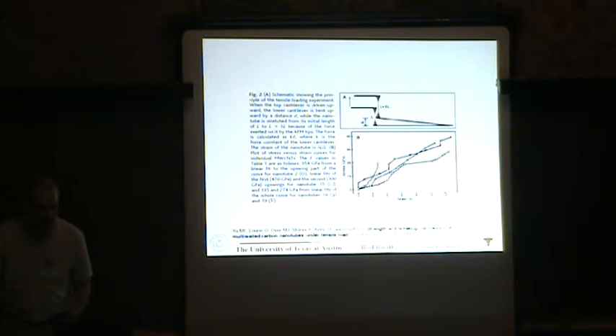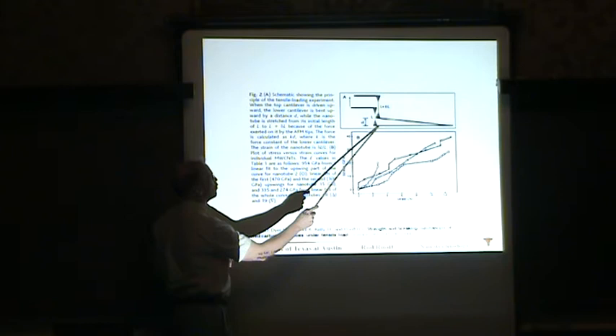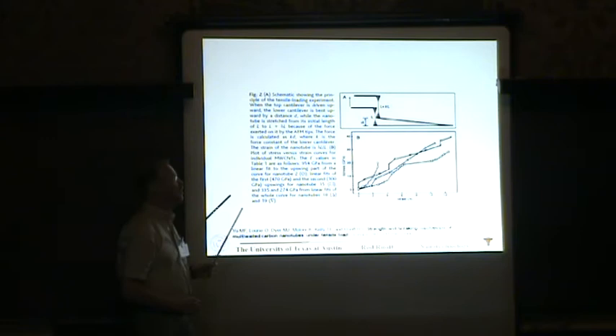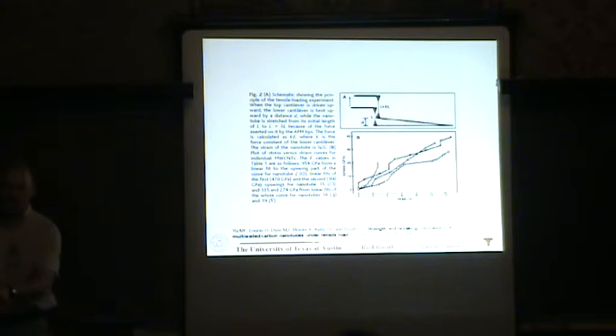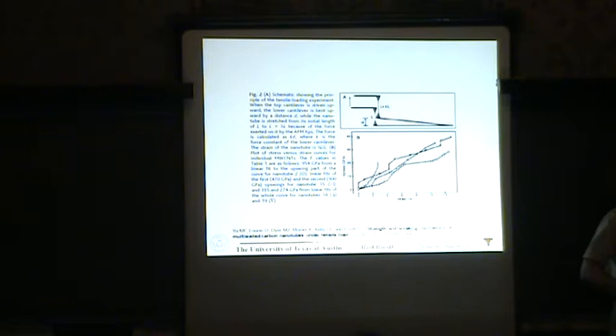And in the experiment, what we're doing is we're driving piezo displacement of one of the cantilevers, for example, the upper cantilever. And we know where this position is. And so the force is simply the stiffness constant of this cantilever measured by its displacement. I think you can see some limitations in this technique as well. It's sort of like using a fishing pole. And as a consequence of using these slender and long AFM cantilevers that have stiffness constants in the right range for the outer shell stiffness and strength to be able to measure good displacements at the experimental image resolution of SEM.